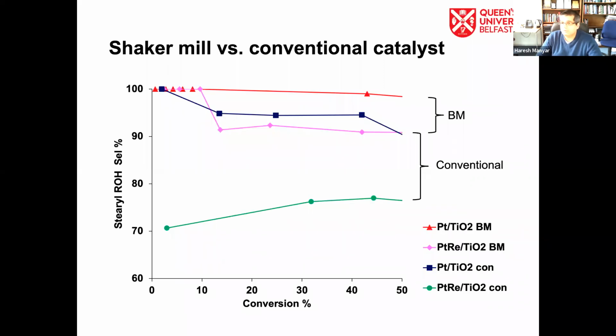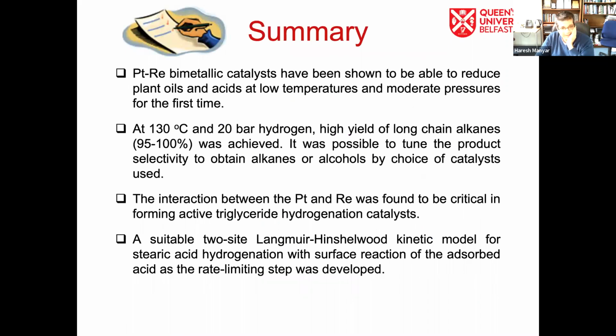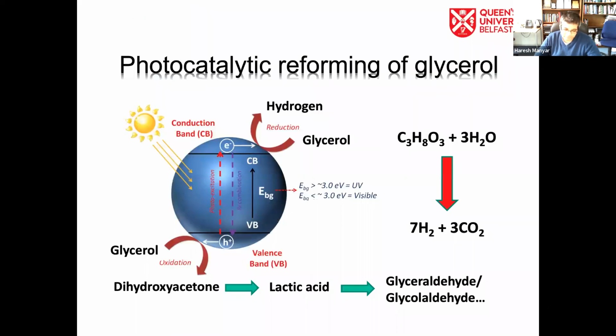And we compared it with the traditional catalytic materials and we've got higher selectivities and higher activities with mechanochemically prepared catalytic materials. So again, another advantage of one of the green chemistry practices in our lab here. In summary, we can make materials using mechanochemistry, we can perform reactions under mild reaction conditions, we can tune the selectivity both to alcohols or alkanes, and we can achieve very high conversions and selectivities at low temperature and low pressure conditions. And these are useful reactions.